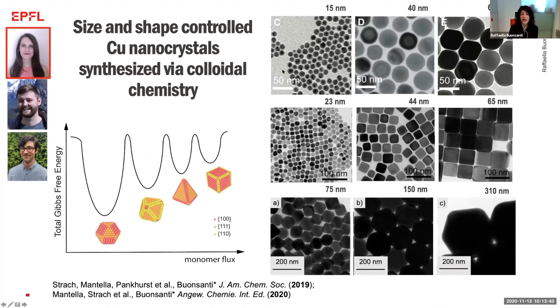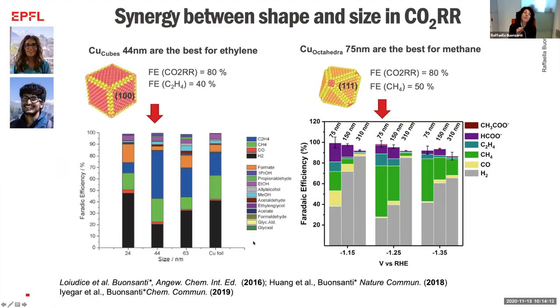What I want to say is that by playing with the chemistry and understanding the chemistry, we were able to synthesize these copper nanocrystals as spheres of different sizes, cubes of different sizes, and octahedra of different sizes. And in agreement with Professor Roldan Cuenya and Professor Strasser, we did find that these spheres produce mostly hydrogen, so they are not highly selective towards CO2 reduction. At the same time, we found a very unique size-dependent behavior of this catalyst.